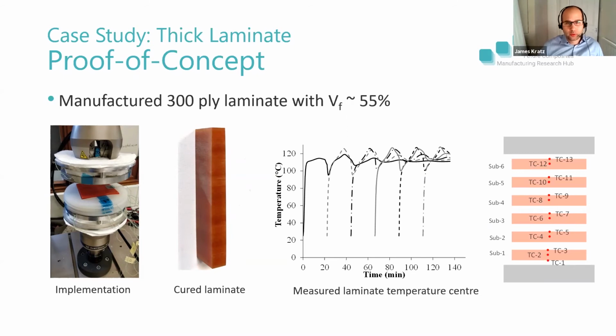The volume fraction was fairly good. This was processed at 1 bar. Yes, it was a flat plate. We processed it in a test machine where the platens were kept at a constant temperature. So this gave us really good control of the thickness that we were trying to achieve and the pressure.